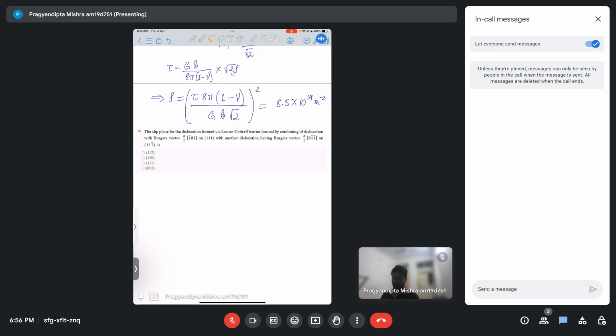If there is a Lomer-Cottrell barrier, or any such dislocation lock, what is happening? Two dislocations are coming and they're locking each other, right? So essentially, first thing first, the Burgers vectors are getting added up. So the new Burgers vector BR will be equal to B1 plus B2. That will be A by 2 1 bar 0 1 plus A by 2 0 1 bar 1 bar. First step, always do this. So you will have A by 2, 1 bar, 1 bar, 0. So that's my Burgers vector.